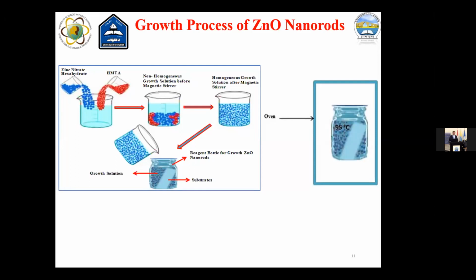After finishing the required growth time for the CBD, the fabricated zinc oxide nanorods were taken out of the deposition solution and rinsed with deionized water to remove the remaining zinc salt, and dried by nitrogen gas.